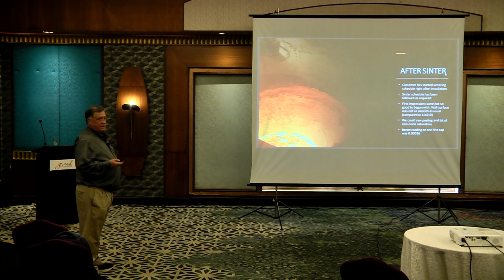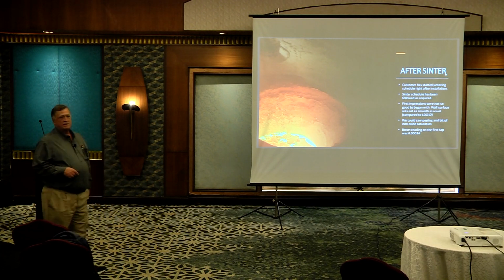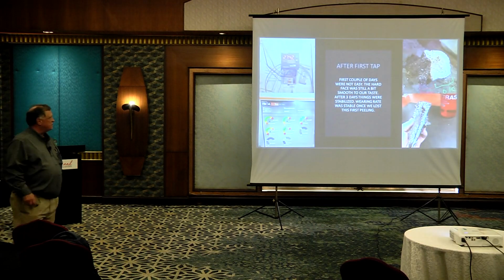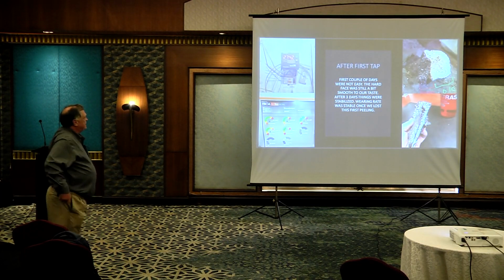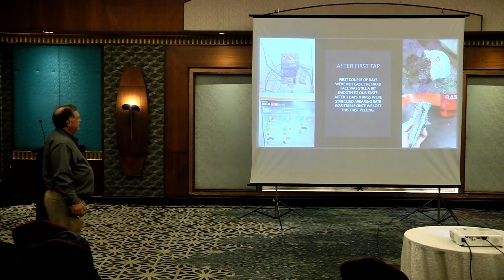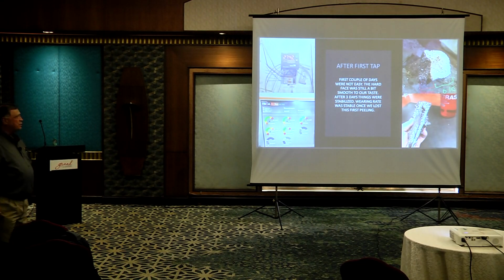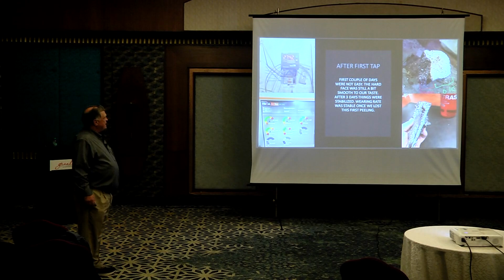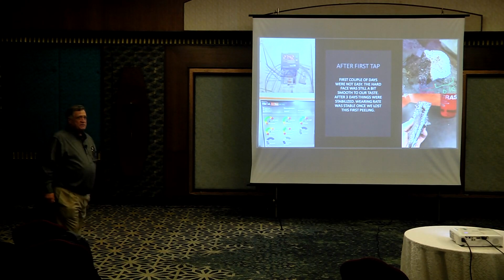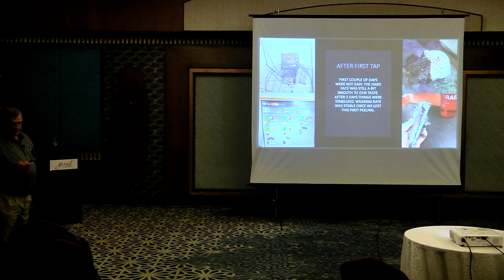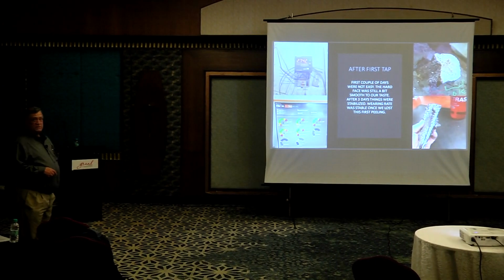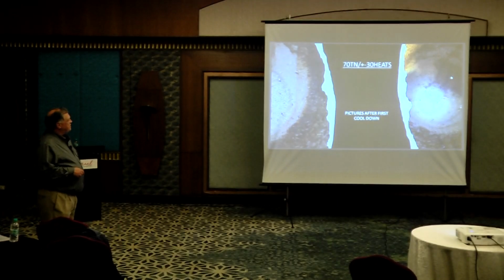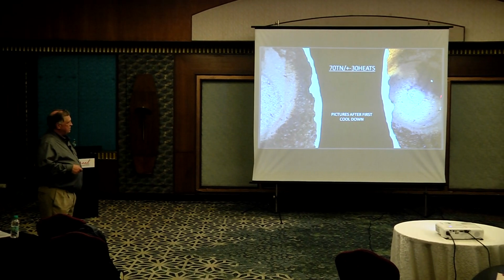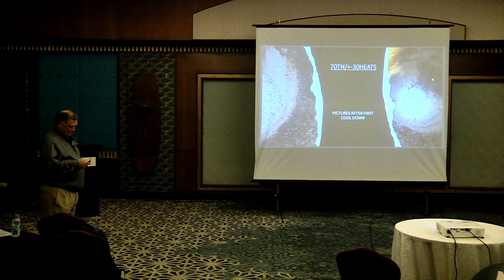But what they did like is that their boron on the first tap was at 0.00036, almost non-existent. And that was well within the specifications of their customer. So, as you can see, first couple of days were not easy. They had hot face issues, which concerned them because it was a new product. We don't blame them whatsoever. After 3 days, they were stabilizing. The wear rate stabilized once we lost the initial peeling of the hot face. And the lining ran quite well after that, actually. It really wasn't an issue. So 70 tons, plus or minus 30 heats. The only place that we still had an issue was in the bottom. There was some of the bottom that was missing, but not enough to cause any harm or damage or even alarm.